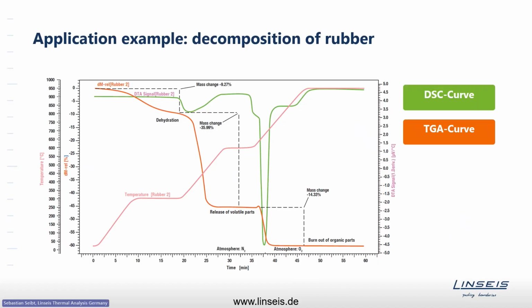At the very end, I have some application examples so that you have a little overview of how that looks. So this example is a pretty simple one. It's a decomposition of rubber. There was a rubber sample that was heated up first in inert atmosphere, in nitrogen atmosphere, and it shows you the decomposition. Again, the orange curve shows you the mass loss or the mass change. The green curve shows the corresponding heat flow signal.